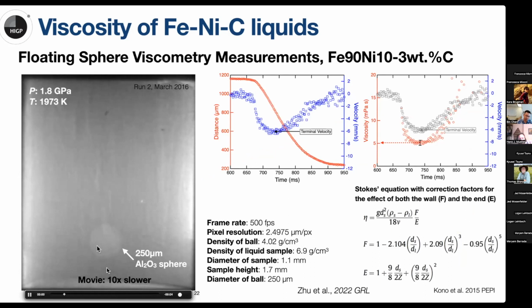This video, which is 10 times slower, shows the floating of the probe sphere in the iron nickel carbon liquid after the sample is molten. By analyzing all the images collected by the high-speed cameras, we find that within tens of milliseconds this probe sphere reaches terminal velocity. From the terminal velocity, we can use the Stokes equations with correction factors to calculate the viscosity of the liquid at high PT conditions.